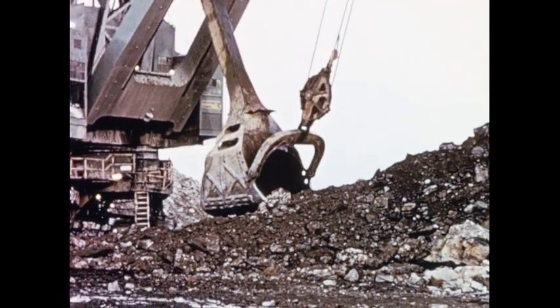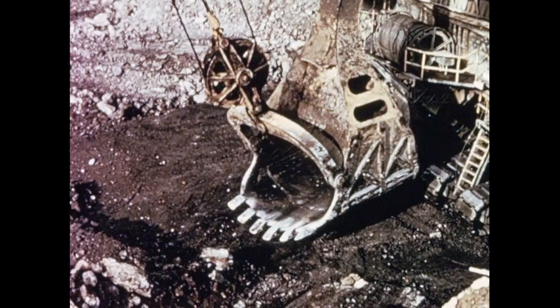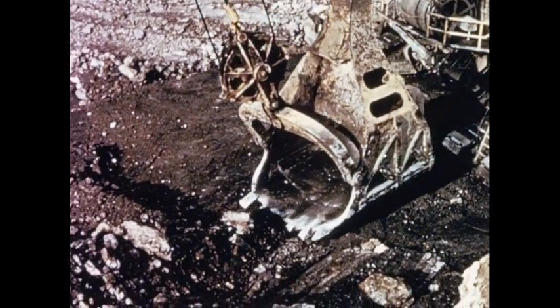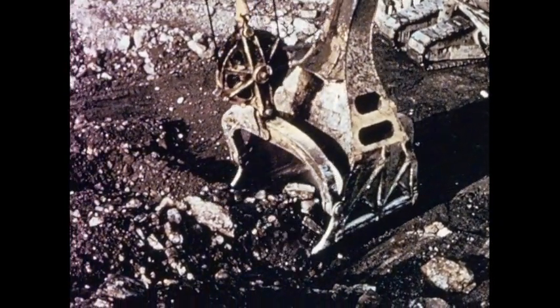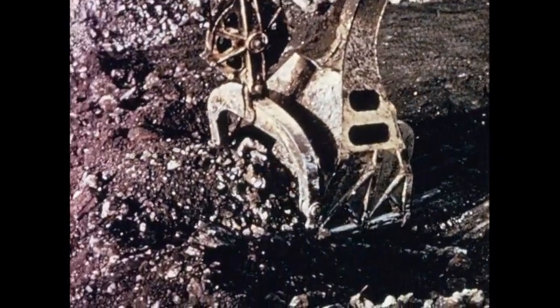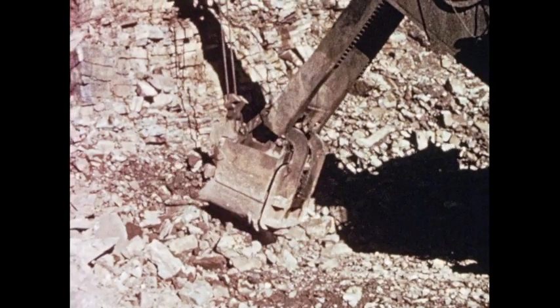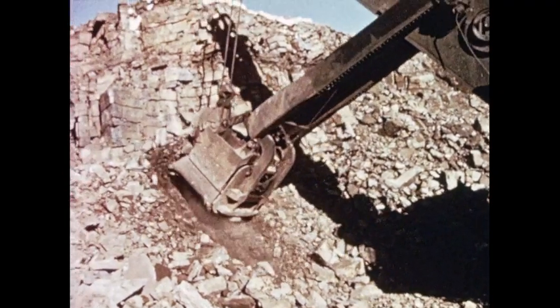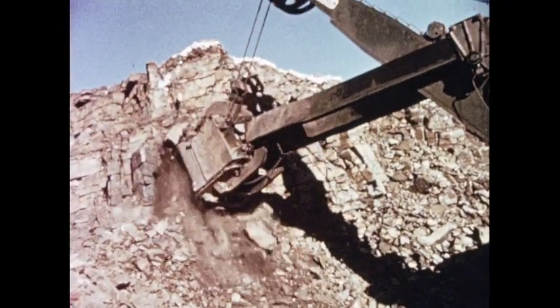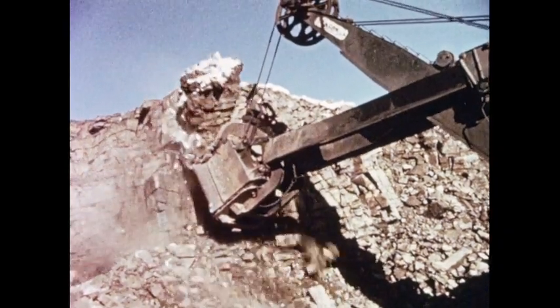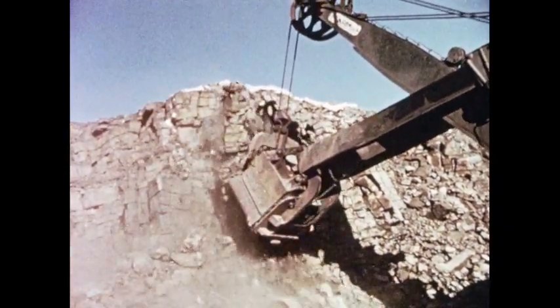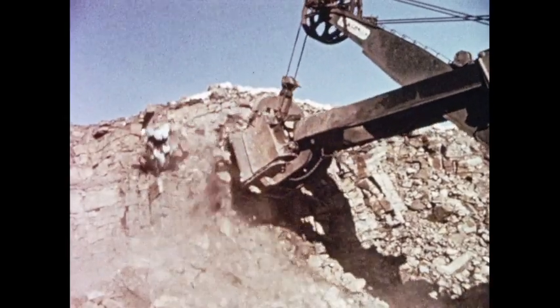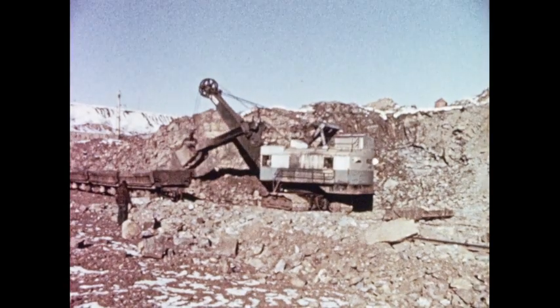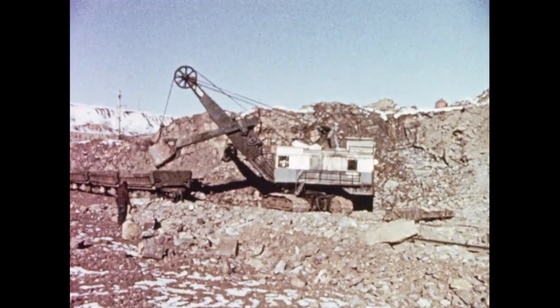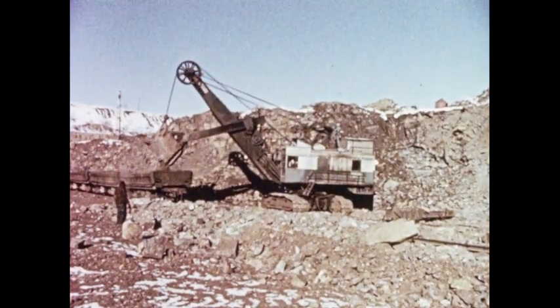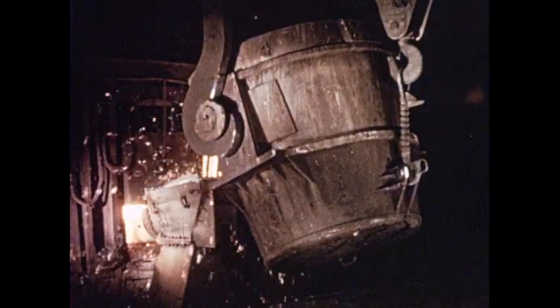At last report, the shovel, working 24 hours a day, 7 days a week, had moved 30 million tons of overburden with extremely low maintenance cost. Also using T1, this shovel has been operating at temperatures as low as 50 degrees below zero in the Minnesota Iron Range. Yet, despite severe stress, impact, and abrasive shock, T1 shows no signs of brittleness, not a single failure in 3 years. In contrast to this low-temperature operation, consider these ladle hooks.